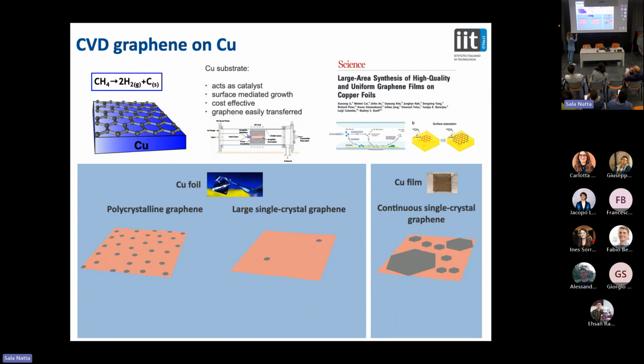But usually you just put your sample here, so your copper substrate, for example, flow the gases, get high in temperature, up to 1000 degrees. That's when you start to have a catalytic reaction, and then basically grow graphene. That's variable parameters: pressure, time, temperature, and gases that you can flow with speed. That's basically what we were doing at very, very early time.